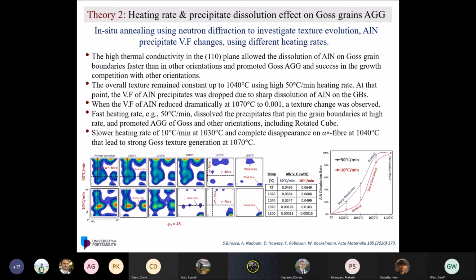When you use a slower heating rate, for example, the lower ODF, we see the texture changing after even 1020 degrees Celsius. The AlN precipitates were dissolved, and the alpha fiber completely disappeared after 1040. And when you look at the volume fraction of the precipitates, which restrict the grain growth until then, when they dissolve, they allow abnormal grain growth to happen.